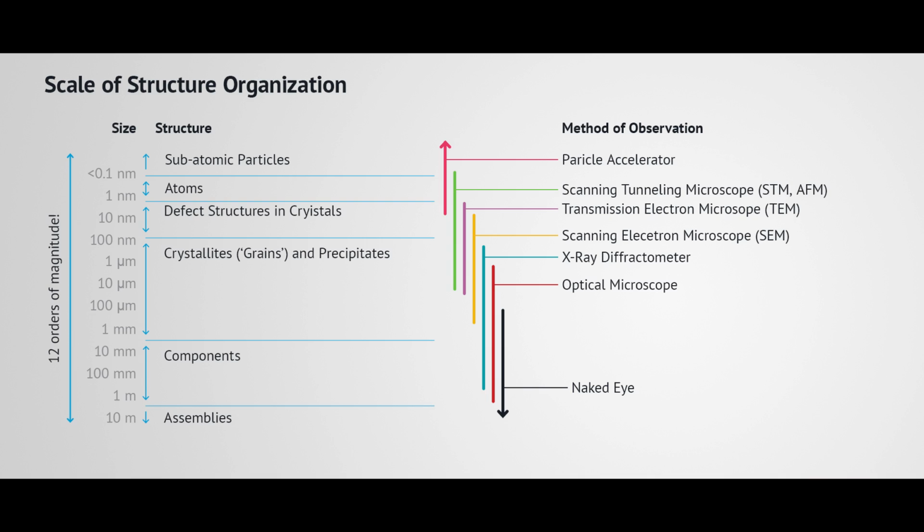So that slide, in some sense, summarizes the whole idea of the lecture: XRD is an extremely useful approach, and with the help of XRD, you can define the phase identity, you can define the lattice parameters of this phase, you can figure out if you have crystalline material or amorphous material, and you can even try to find out the percentage of different phases, so-called quantitative XRD analysis, which is a little bit more complicated, but in any case, even the percentage of phases which exist in your material.